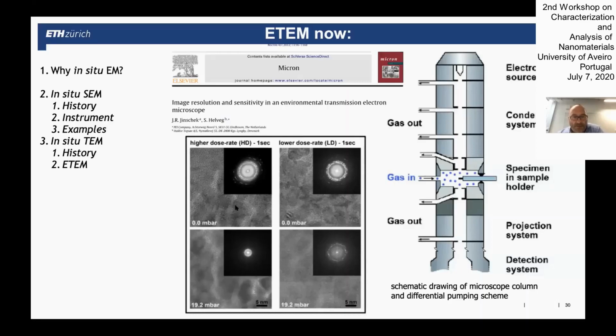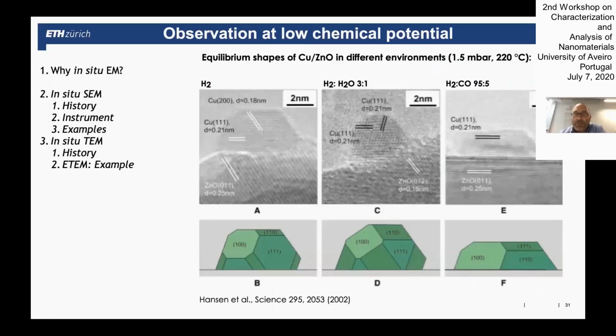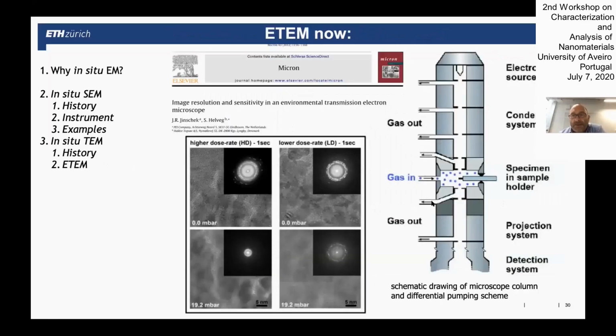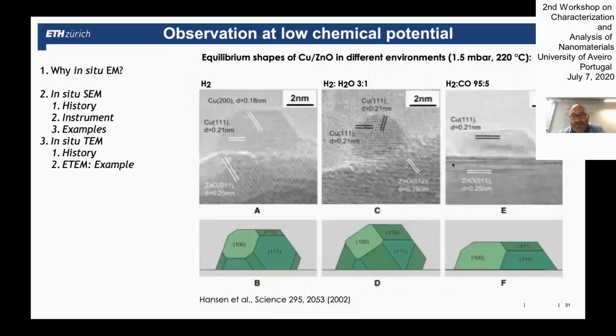At the beginning, you have your lattice fringes that is evident from the Fourier transform. You see these rings and spots. But when you introduce, say, like in this case, 20 millibar, you basically lose all the lattice resolution. It, of course, depends also a bit on the type of gas that you introduce and so on. But if you want to learn about this, just please read this paper of Jörg and Stig Helveg. There are also some very important studies that have been done with such environmental TEMs. This is called environmental TEM. This is really a special TEM. It's called environmental TEM because it has this differential pumping system here. You cannot go up to infinitely high pressures, so just a few millibars, but you can still get high resolution.